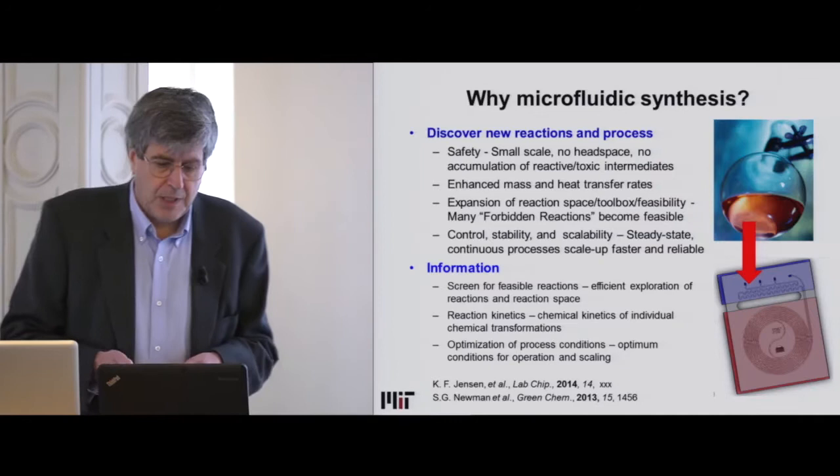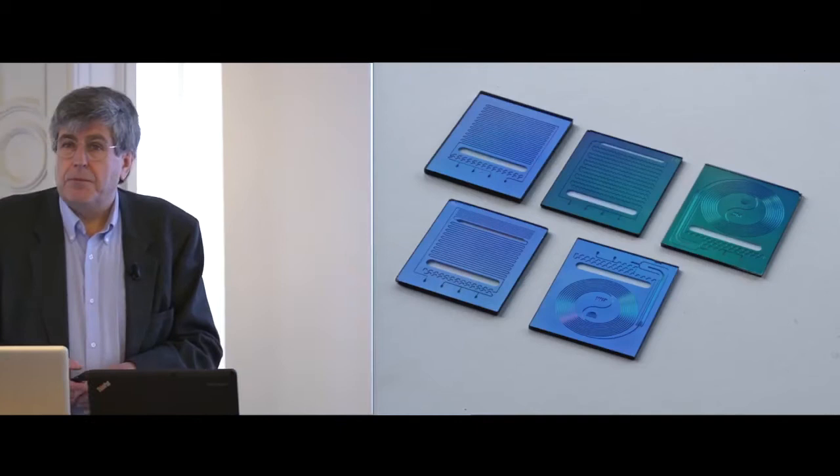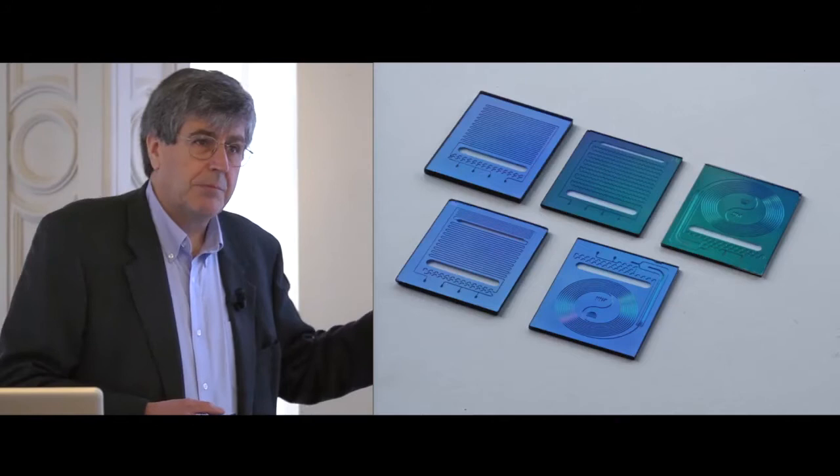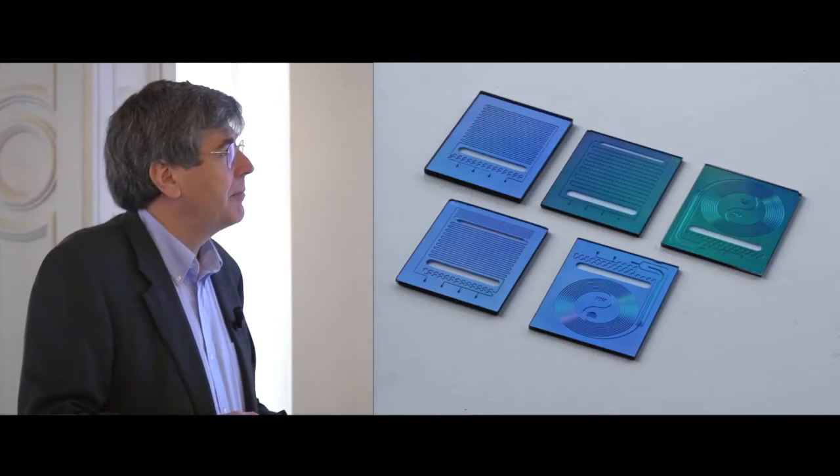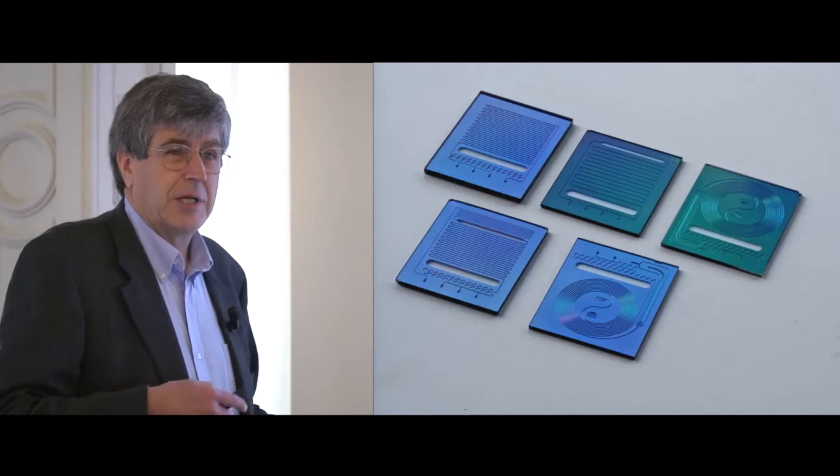Much of my talk will deal with the reactors we use because of the issue of chemical stability. We tend not to use PDMS, but reactors built by photolithography in silicon and then anodically bonded to glass — to Pyrex — which makes them able to withstand very high pressures and temperatures. It's really your own imagination that limits your design in these particular cases.